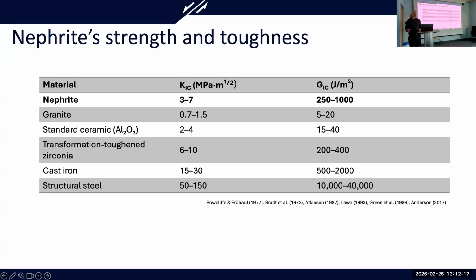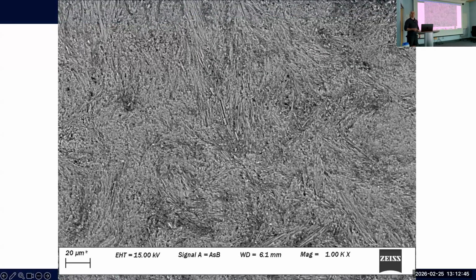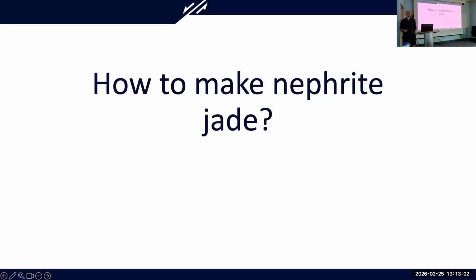For the geologists, this is a material that's crystallized in its metastable form as a ceramic. When a fracture propagates, it induces the phase transformation with a volume change that seals off that crack. So we're dealing with a natural material that compares to some of our best, most advanced ceramics, kind of in line with cast iron in terms of toughness. And that really all comes down to the microstructures, to those fabrics. And it raises an interesting question. Could we leverage this kind of natural material, or at least the processes in which they form, to make stronger modern ceramics? We'll get to that eventually in the end, but this is ultimately the question we'll be addressing: how do we make this nephrite jade?